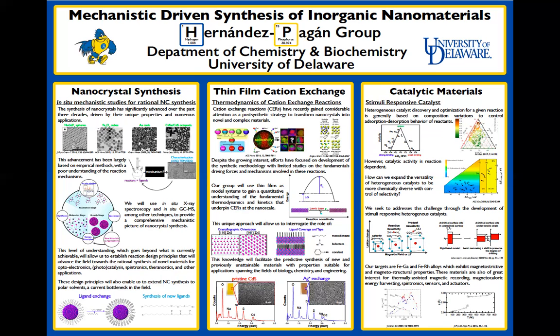So if you take a look at the preliminary data shown at the bottom here of cadmium sulfide silver exchange, you can observe a color change from yellow to brown and the subtle addition of a silver peak around 3 keV in the EDS spectrum, both of which are indicative of a cation exchange reaction.